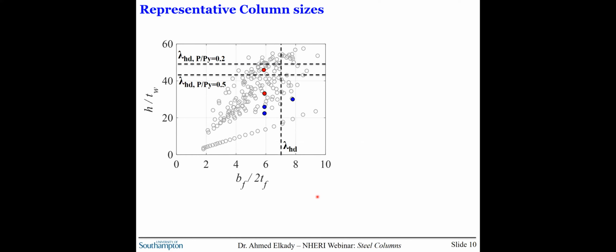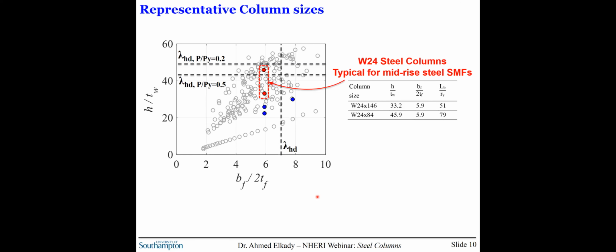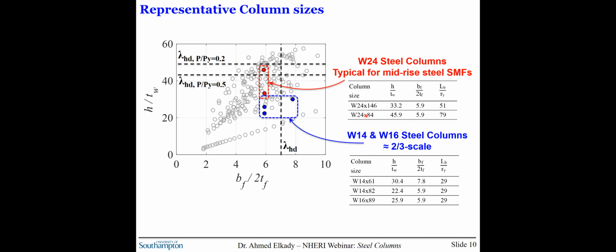Looking at the cross-section space for wide flanges, for the testing, we started by selecting representative column sizes. For the full-scale testing program, based on code-compliant archetype mid-rise steel office buildings, we chose W24x146 and W24x84 to be tested. For the larger scale testing, we selected 3 sizes from W14 and W16 as shown here. These are equivalent to the moment frame columns in mid-rise steel buildings, but at a 2/3 scale. Probably you already noticed from this plot that the main geometric parameter we are varying here is the web slenderness ratio. And essentially, we found this to be the parameter with the most impact on the cyclic behavior of the column based on an exploratory numerical assessment.